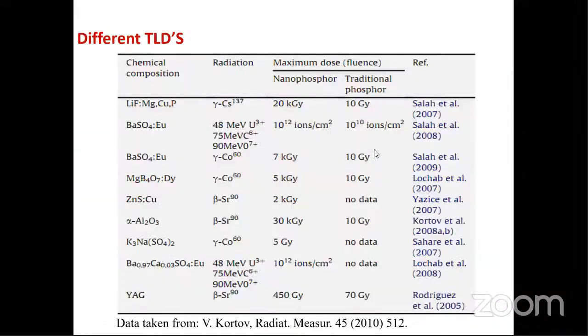These are the recently developed TLD materials. Nanophosphor material goes up to 20 kilogray, and traditional phosphor, meaning the primarily developed phosphor material, indicates 10 gray. Which was the data taken from? This is the literature from which I have taken this data.